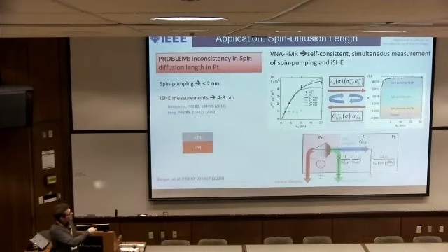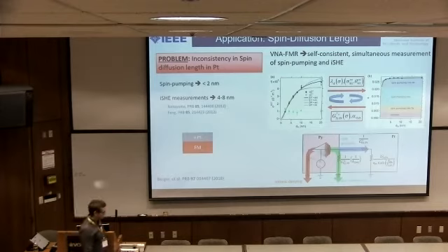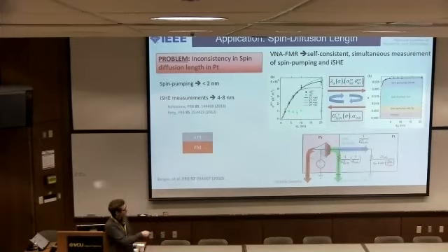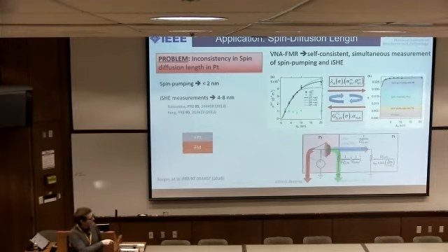In the spin orbit torque measurements here, we're only measuring the spin pumping contribution. It's not sensitive to this at all. And so it turns out we're now actually able to separate these two. And that has 2 consequences. One is that, because we can separate them, we can start engineering that interface better. So we can more efficiently get all that angular momentum into the platinum to do something useful, or across that interface.